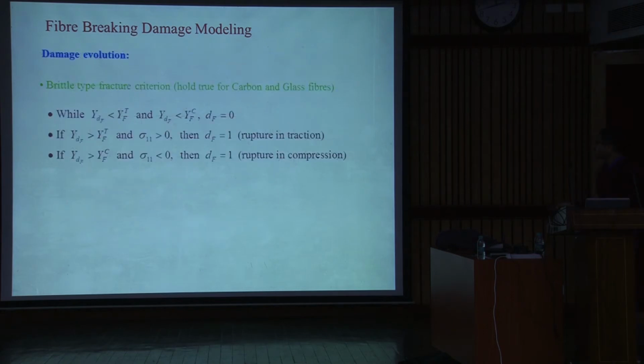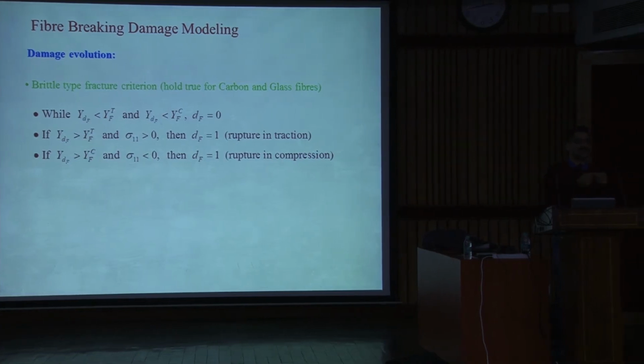Okay. Then if the stress in the fiber, direction 1, that is along the fiber, is tensile, then I will compare it with the critical thermodynamic force for the fiber in tension. If it is more, then I will have this damage indicator as 1. Why am I putting 1? Because for carbon fibers and glass fibers, the failure is brittle. So either it will go on stretching and then ultimate failure. There is no failure which is increasing step by step. It is either intact or it is complete failure. So that is why you will have either 0 or 1, both in tension and compression.